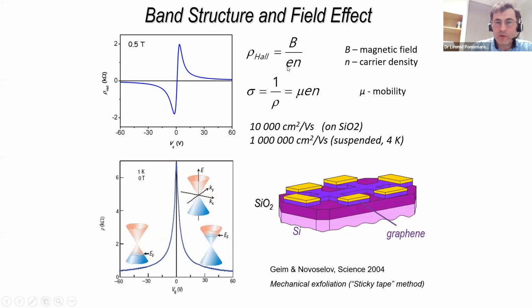Right, and once we know the density of charge carriers and we know the resistivity, which can be converted to conductivity, we can calculate another important parameter, especially for engineers, which is called mobility, which plays a very important role in making semiconductor devices, and especially how noisy they are and how fast they are. So it was realized already in 2004 that mobility of charge carriers in graphene is quite high. So 10,000 centimeter square per volt per second. This is the standard unit in which mobility is measured. Also, it's not an SI unit. And a few years later, it has been shown that this mobility can be even increased to a value of 1 million. Also, for that, we have to go first to low temperatures, and then we have to make graphene suspended. So we have to remove silicon oxide because it's not a very good substrate for graphene.